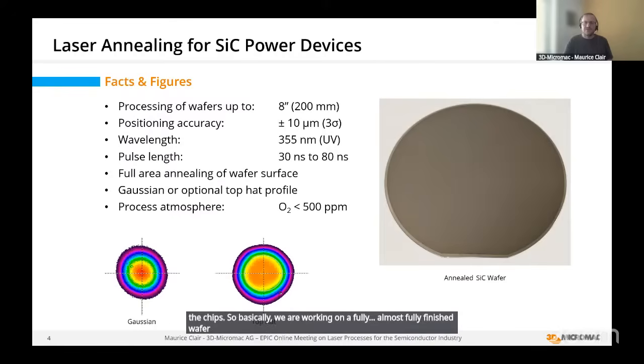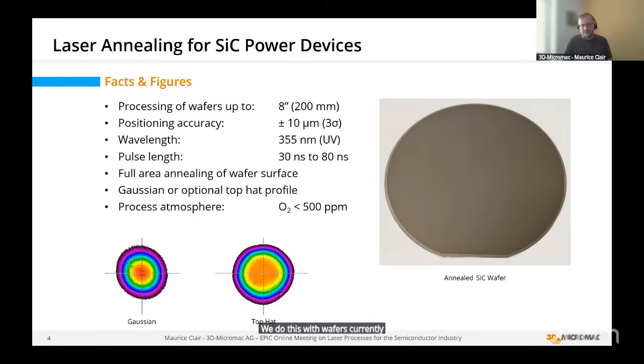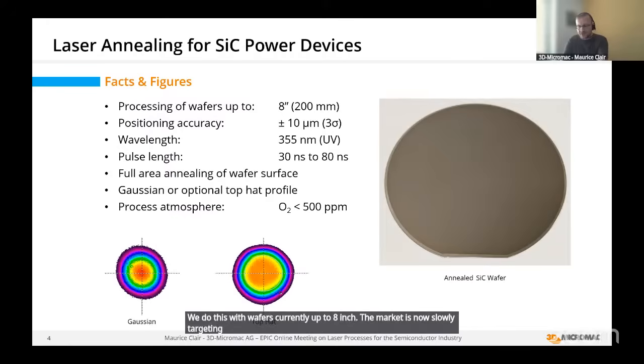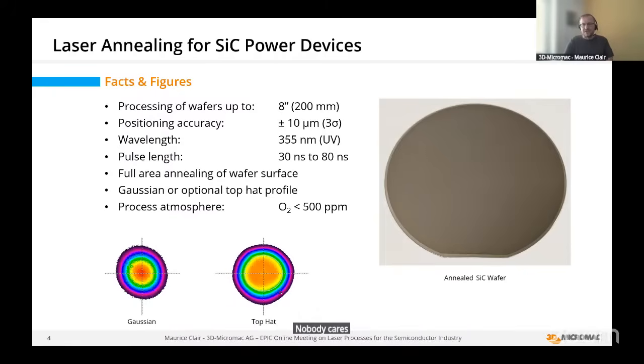We do this with wafers currently up to 8-inch. The market is now slowly targeting 12-inch silicon carbide wafers, which are now available from China, but they are far from production so far. And this is, in general, a very coarse process. The actual positioning accuracy of 10 micron, nobody cares about. As you can see, the whole wafer is processed with an edge exclusion of around about 1 millimeter.